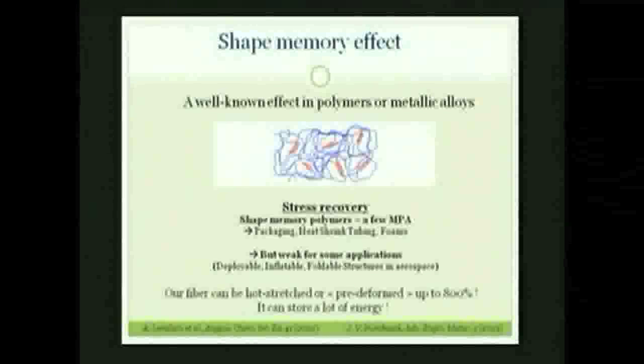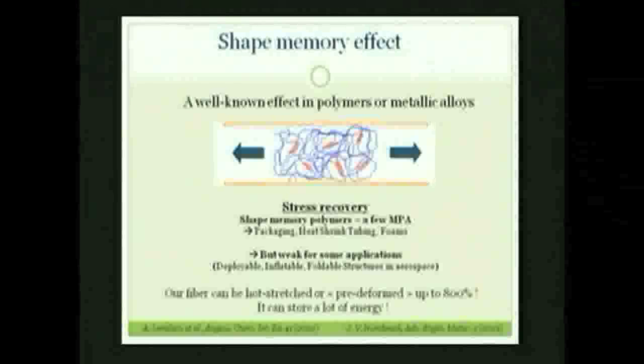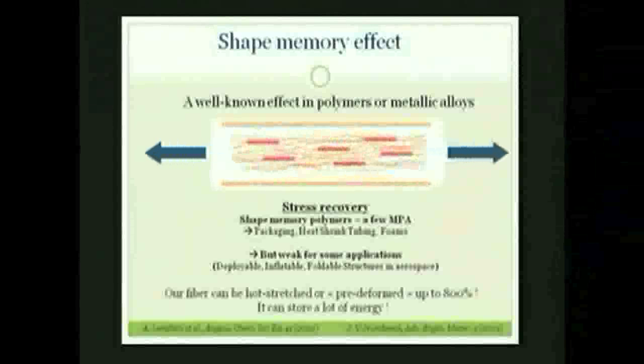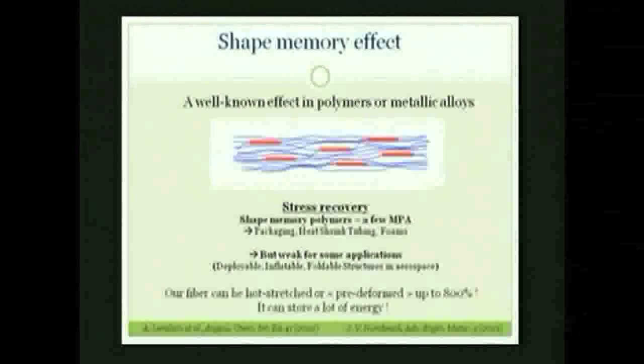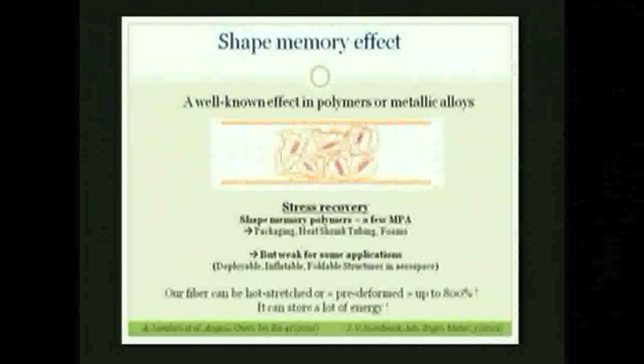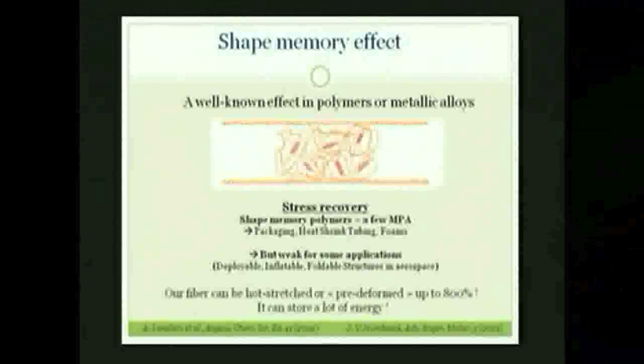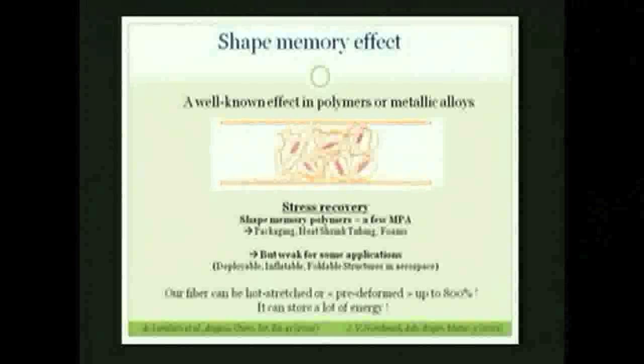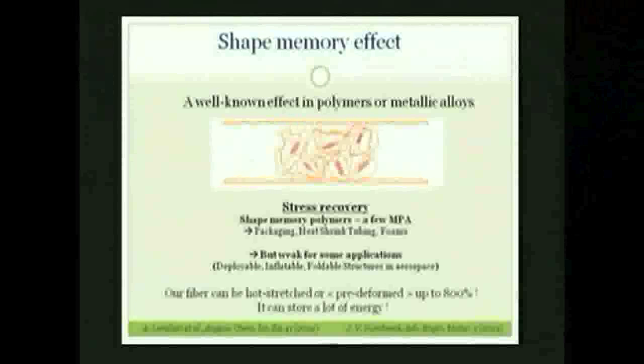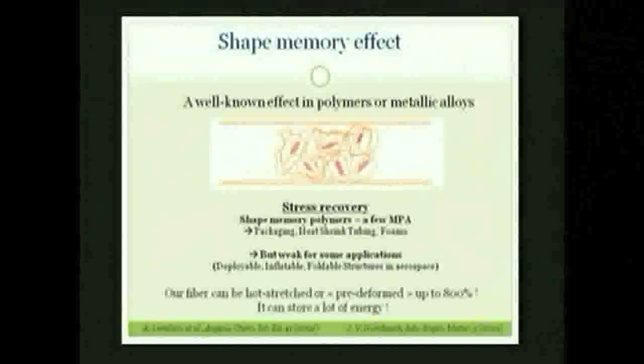When you hot stretch a polymer like this one, so you heat it, you stretch it. So basically what you do, you align the crystallites of the polymer and the chains within the polymer. Then if you cool down this polymer, keeping the stress, okay, you will have an aligned structure like the fibers, like what we do with the fibers. Then if you reheat the polymer, the chains want to go back to their initial shape, and you will observe a global contraction of the polymer, okay? The polymer stores energy during the hot stretching process, and it gives back this energy when you heat the polymer again. And it's a very well-known effect.